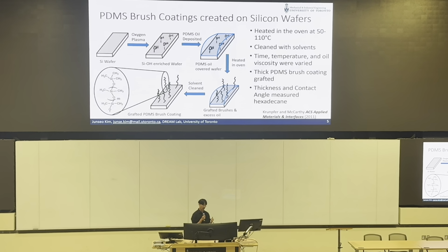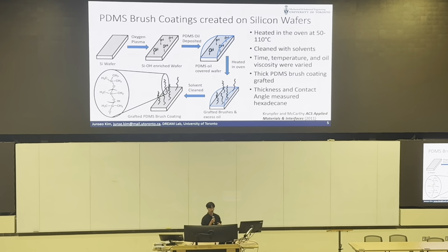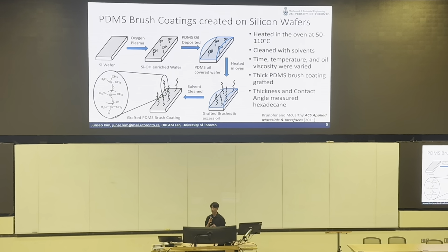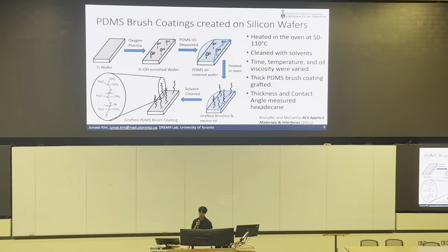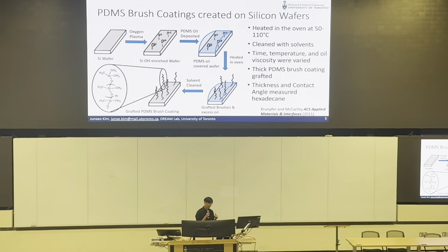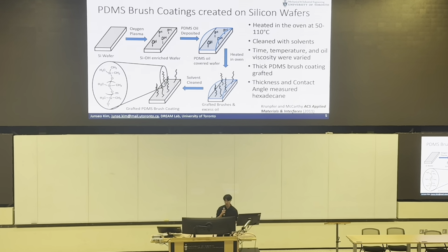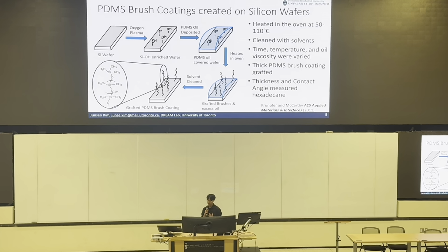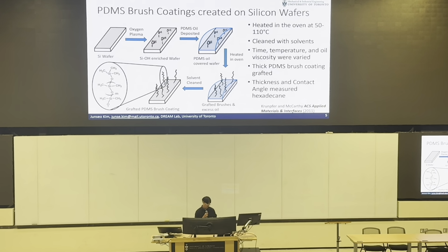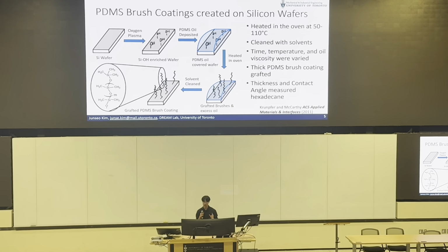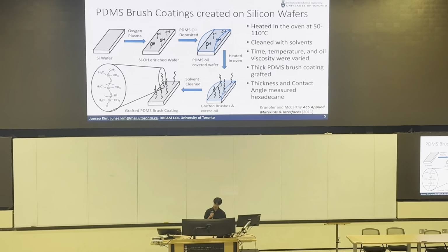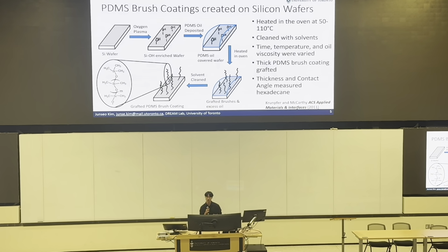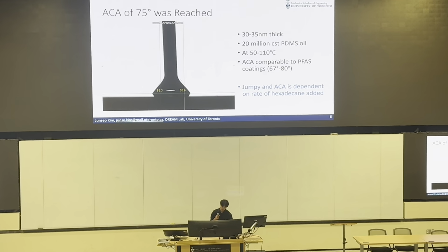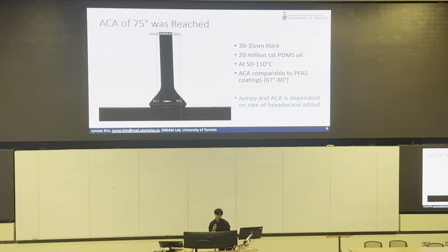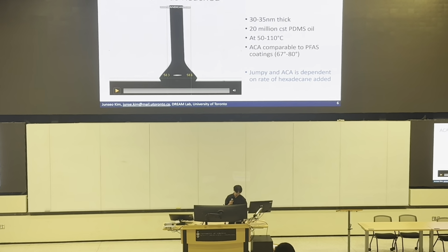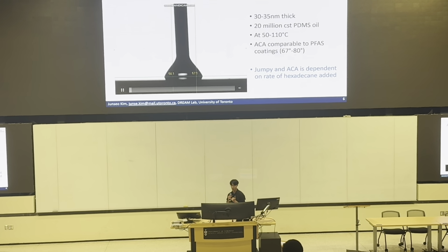Once the brushes are grafted onto the surface, there's going to be some excess oil. I clean it up with solvents, some polar and non-polar solvents that are arbitrary. And then I will have this grafted PDMS brush coating that's thick and desirable. The thickness and contact angle were measured using the goniometer and ellipsometry. Something interesting: an advancing angle of 75 degrees was reached with my coatings.